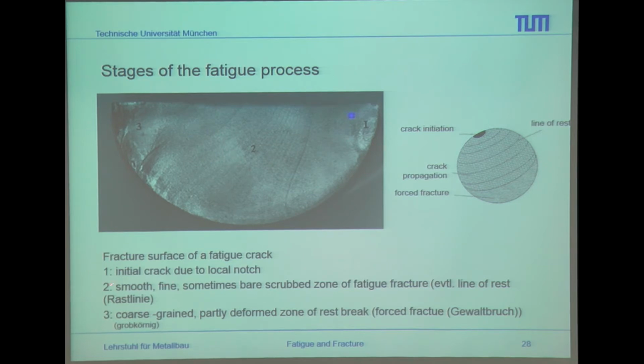The crack propagation has some smooth and fine, sometimes bare, scrubbed zones of fatigue fracture. In this zone, you can see some rest lines. These are always the darker lines. You have the sinusoidal loading, but still the crack propagation is not continuous. You always have some lines where the grain structure has some resistance. At this part, you have what we call a rest line, so the crack is not growing as fast. And afterwards, if this resistance is broken again, the crack propagation starts again, and another rest line occurs. As you can see here, the surface is also quite smooth and looks quite fine.